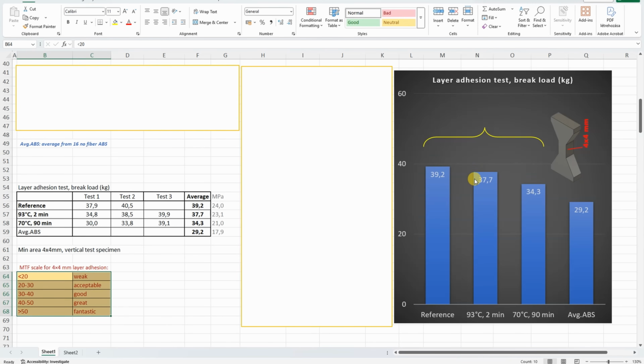About the cleaning methods, this was that short boiling method, very minimal difference, and here it was exposed to this 70 degrees Celsius almost 90 minutes, which is quite long. And what we can notice here is some bigger jumps, standard deviation between the numbers, so we can see even some bigger numbers. Maybe the objects are exposed differently to this cleaning 70 degrees Celsius water, but anyway, this is still a good layer adhesion.